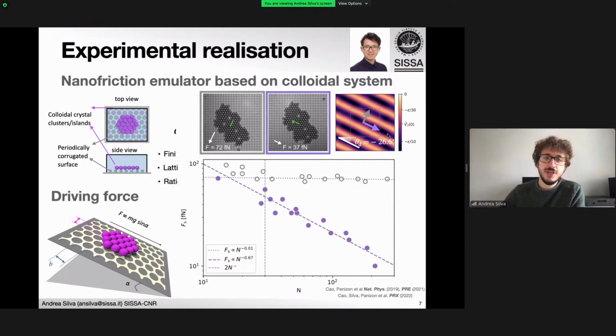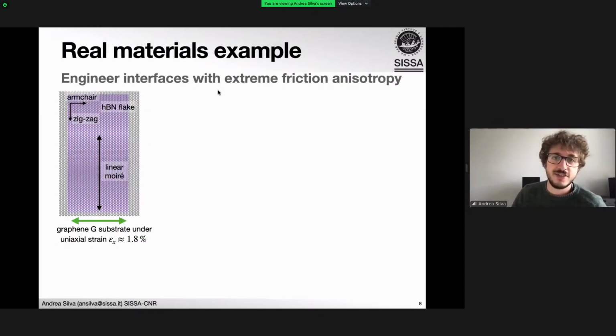One last thing that we can do is reverse engineer this process and design an interface with an extreme friction anisotropy. In this case, we took a graphene substrate and uniaxially strained it along X by about 1.8%, which is well within experimental values. And then we place an hBN flake on top of it. We can go and see what happens as the size of the flake increases.